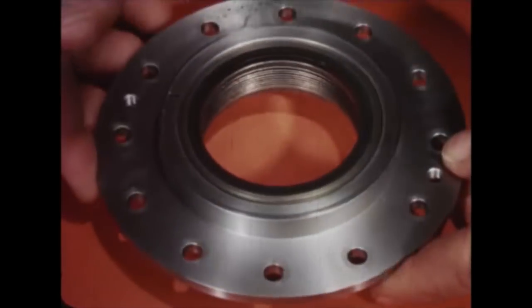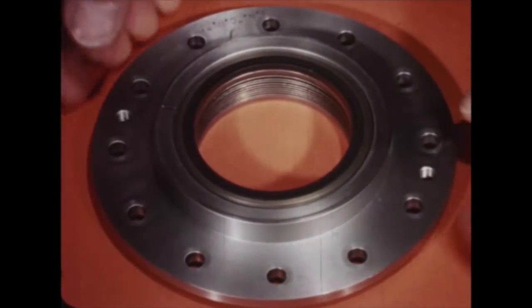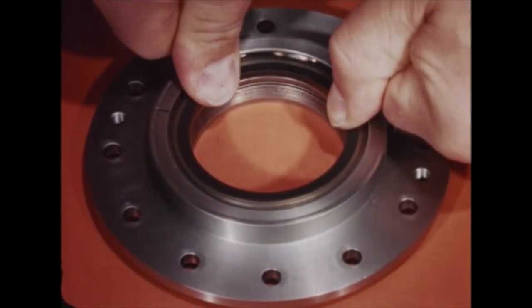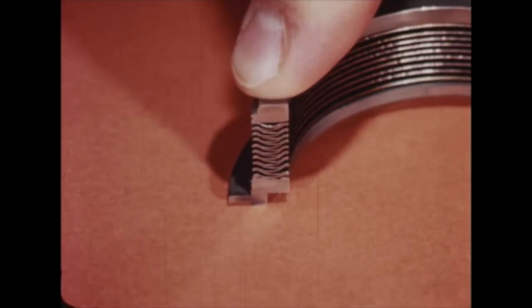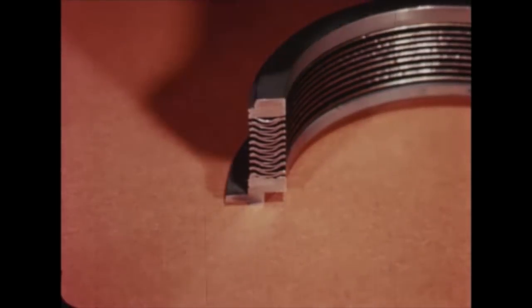The tests were initiated as a result of the failure of the seal to perform satisfactorily at the 200 K level after having performed successfully at 188 K. Since the failures experienced were fatigue failures, it was felt that a resonant condition between seal cavity environment and bellows natural frequency may have existed. Results of the vibration tests and seal cavity environment studies indicate that the failures are not due to resonant condition. Studies on this problem are continuing.